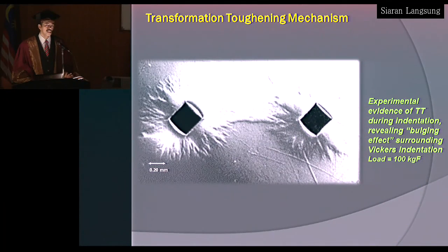And these are experimental evidence which I have obtained through my research to show the effect of transformation toughening. What you have seen there is a Vickers indentation made on the material. And the load applied for this particular ceramic is about 100 kilogram force. Now, what you don't see is the crack emanating from the diagonals of the indent. But instead, what you see is a surface uplift phenomenon. So this shows that transformation toughening has taken place, and the material has nowhere to move except upwards, the free surface.